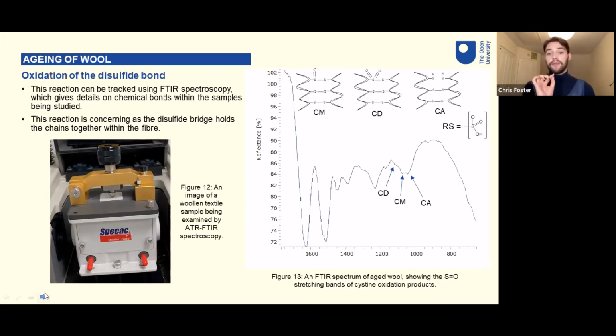And in this region with the arrows labelled, these are the sulfur-oxygen double bonds. They give quite a strong band in the spectrum, so we can track these easily. And as you can see, each cystine oxidation product, so the cystine monoxide, dioxide, and the cysteic acid, all give slightly different bands because they're in a slightly different environment.